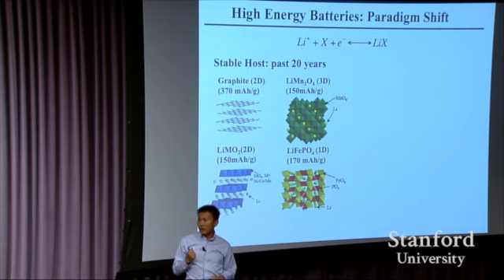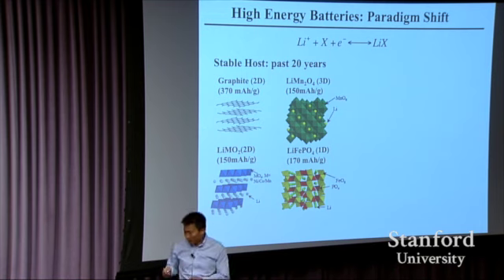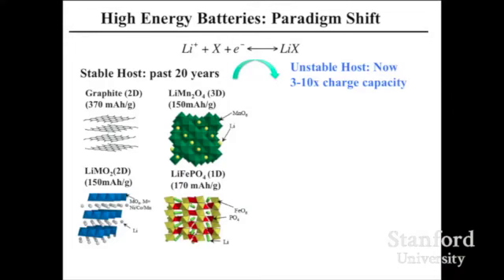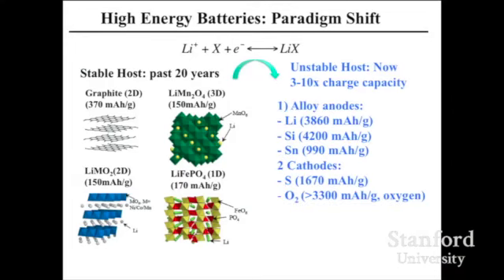You need 3 more times of lithium ions. So now you put a lot of lithium ion coming in. There are new materials, they can do 3 to 10x. For example, lithium metal by itself, silicon and tin as anode, and sulfur and oxygen as cathode.